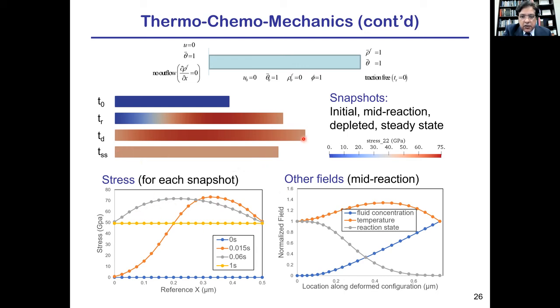We can also look at this phenomenon from the point of view of fluid concentration. On the right end, fluid has fully permeated, but it has not yet reached this end. So the fluid concentration is 0 there. Likewise, temperature is higher where the action is taking place and lower on the other side. And this parameter here is the reaction state variable. When it is 0, it means this material is completely depleted at this particular point, and 1 means that the reaction has not reached the left end yet.